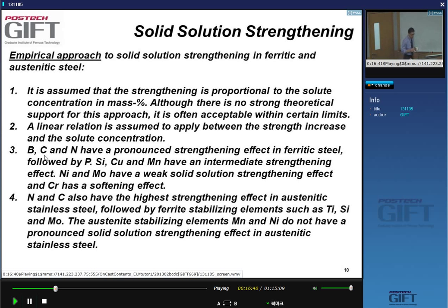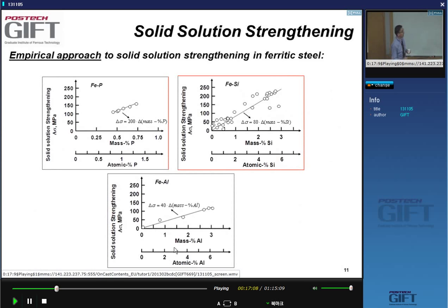But as a rule, interstitials increase the strength. So carbon and nitrogen have high strengthening effects in austenitic steels. And then silicon, titanium, and moly have a strong intermediate strengthening effect. Manganese and nickel do not have a pronounced solid solution strengthening effect in austenite. All right. And so we have lots of data